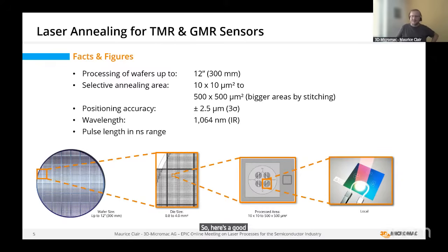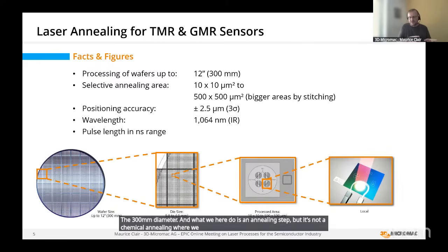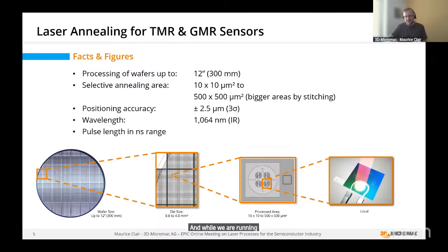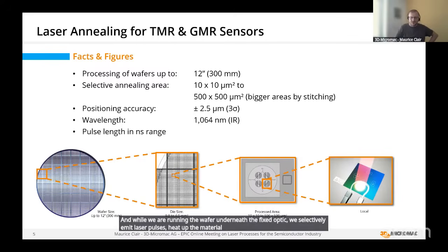And we are doing this on by now 12-inch wafers with 300 millimeter diameter. And what we here do is an annealing step, but it's not a chemical annealing where we change the chemistry on the surface like in the last one, but we do physical annealing. And we actually expose the sample to a strong magnetic field of 600 millitesla. And while we are moving the wafer underneath the fixed optic, we selectively emit laser pulses, heat up the material above Curie temperature, and the material cools down very fast because the energy is deposited very locally.